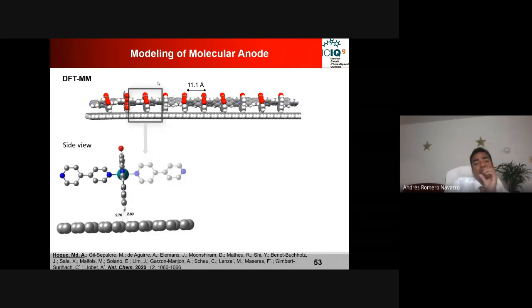And if we look at one particular molecule, you see at the bottom is basically the carbon material, and on the top we are saying this wheel-based one is actually the polymer. So in the side view, I have a bit of a zoomed version here. This is the carbon-based material, and here we have one particular unit of that molecule. What we found is that all these molecules have this CH bond. You see? The white color I'm showing is the CH bond.